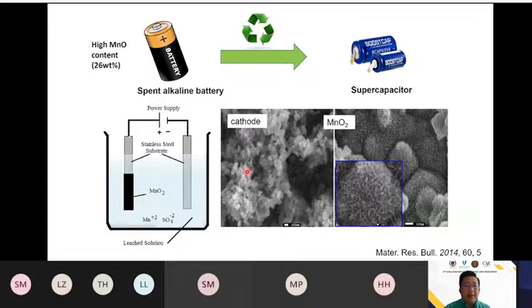In every piece of spent alkaline battery, there is actually 26% manganese oxide. If we just discard it, it is going to cause an environmental issue, and at the same time, we are losing our metal. So we perform an electrochemical treatment to recycle this manganese oxide. If you look at the cathode material, before the treatment they are clumped together. But after we run the electrochemical treatment, this manganese oxide can be oxidized back into manganese oxide in a nanoflower shape.